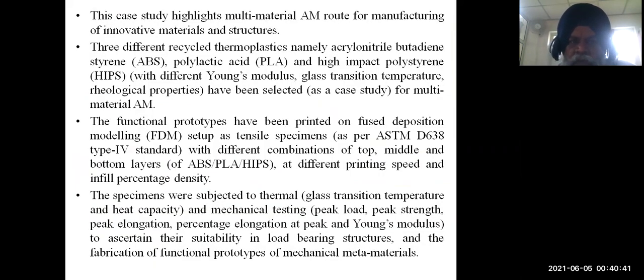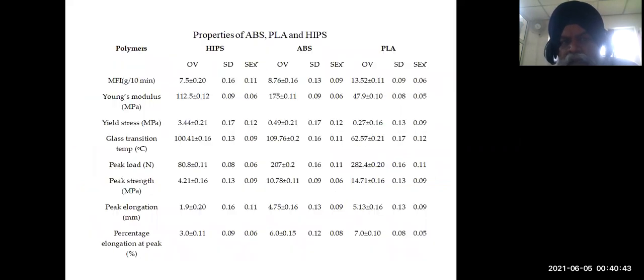To put our point, we try to explore some combination of multi-material printing. So we selected three materials, HIPS, ABS, and PLA, just for demonstration purposes. The basic difference was they have a lot of difference in their MFI. Like HIPS has an MFI of 7.5, ABS MFI of 8.7, PLA MFI of 13.5. This is in gram per 10 minutes. Then there is a significant difference in their Young's modulus, their glass transition temperature, peak load, peak strength. All properties were significantly different, right?